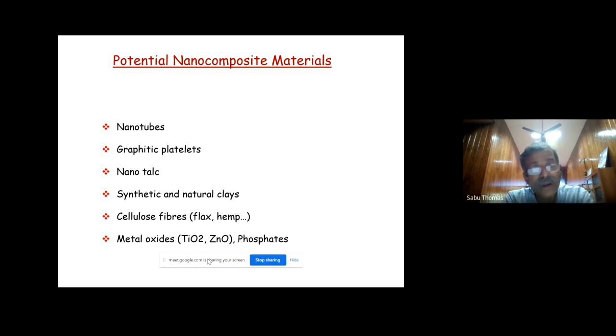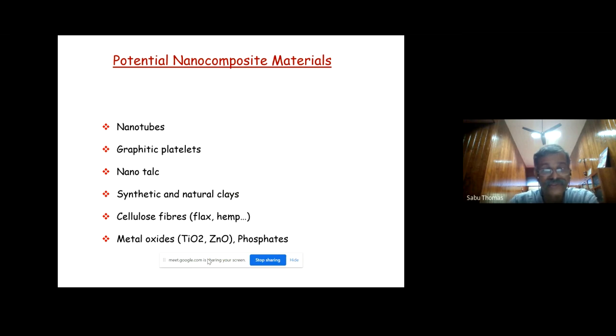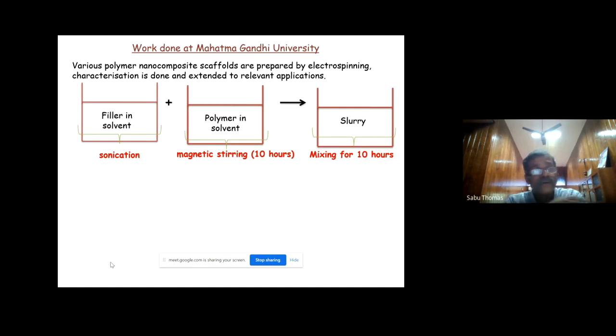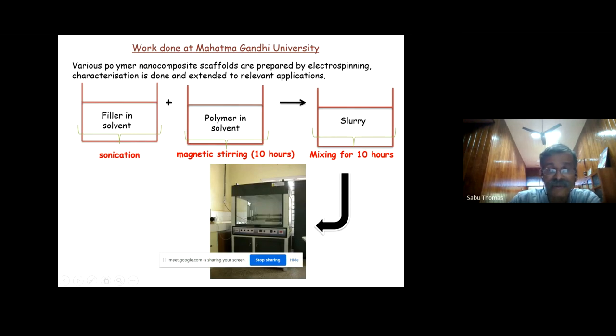They provide lots of advantages. So what are the nanostructures we use in my laboratory? We use nanotubes, graphitic platelets, nanotalc, synthetic and natural clays, and cellulose fibers. Look at cellulose, we are very active. You can see we have a very nice book on cellulose in cooperation with my colleague in the United Kingdom. So we work quite a lot on nanocellulose. Different types of metal oxides. How do you make them? We make solutions of polymer and the nanostructures, sometimes bioactive agents, nutraceuticals. Then we go for the electrospinning process. You can see the electrospinning setup in my laboratory.